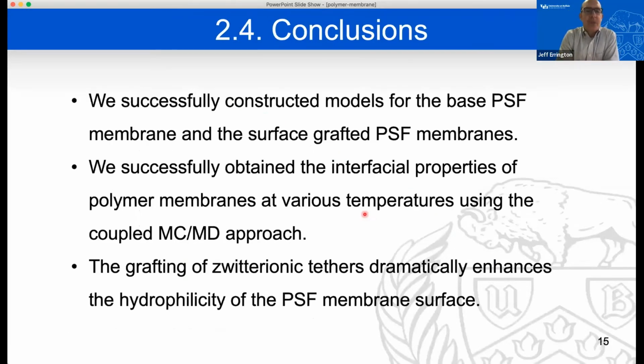All right, so to conclude this first part, we were able to successfully construct models for this base polysulfone membrane, as well as the grafted surfaces. To be honest, we really didn't know where to start with respect to this. This was sort of a new area for us and there wasn't a lot in the literature. So we'd certainly be interested in feedback in terms of whether this was a reasonable thing to do, or suggestions in terms of other ways of creating such models moving forward. And then we were able to successfully obtain the interfacial properties of these systems using this sort of coupled molecular Monte Carlo molecular dynamics type of approach. And in terms of the actual polymers themselves, we found that the systems that had the Zwitterionic tethers had much stronger affinity for water. They were much more in the sort of wetting scenario relative to the other systems involved.